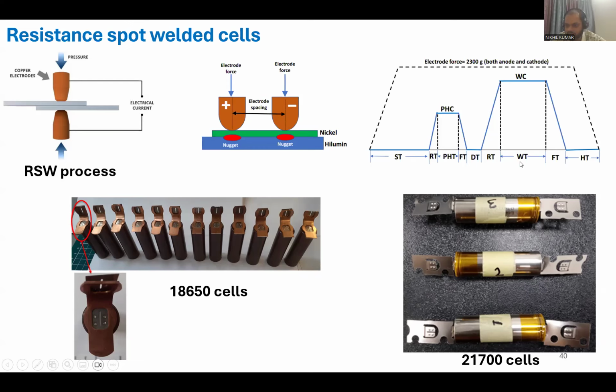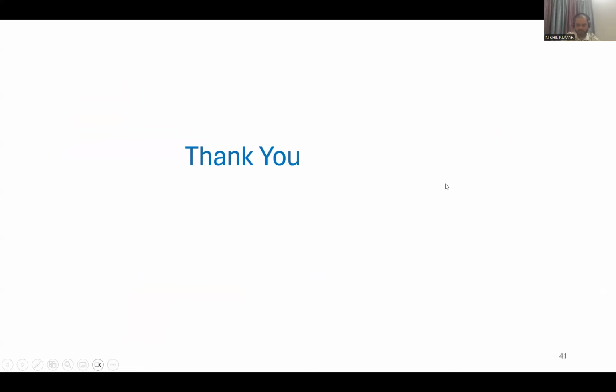And this short notation shows the process parameters applicable to the resistance spot welding process. WC is the welding current and WT is the welding time. Similarly, this is the hold time and squeeze time. This is the preheat current; it can be done with a preheat and then the main current. I first did a lower preheat current and then I did the welding. It can be arranged in a different manner as well. You can also do more preheat and a low welding current. It is up to you what kind of material you are using, whether you want to break the oxide layer first and then do the welding. That kind of concept is used here. Yeah, thank you.